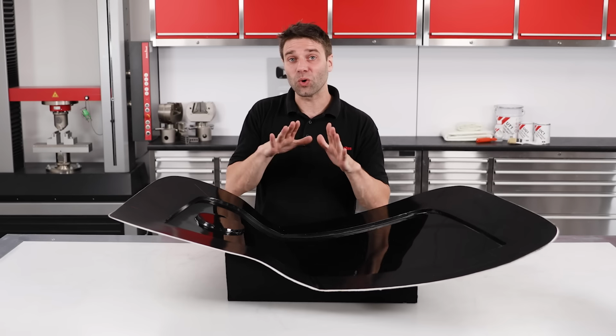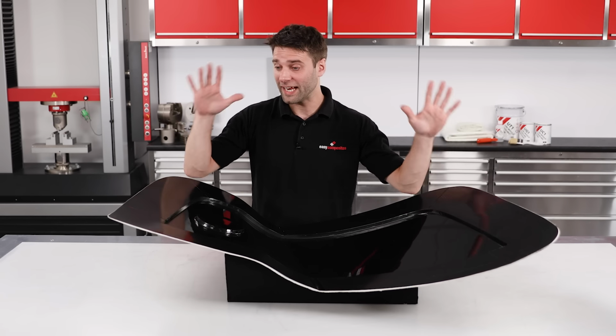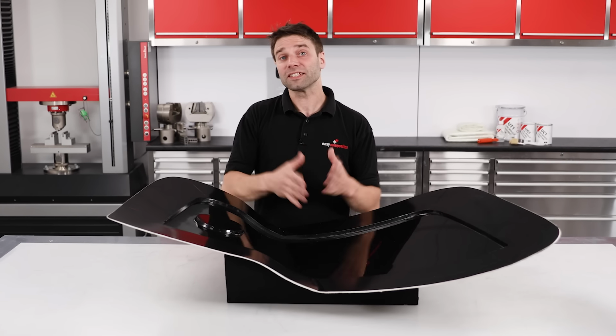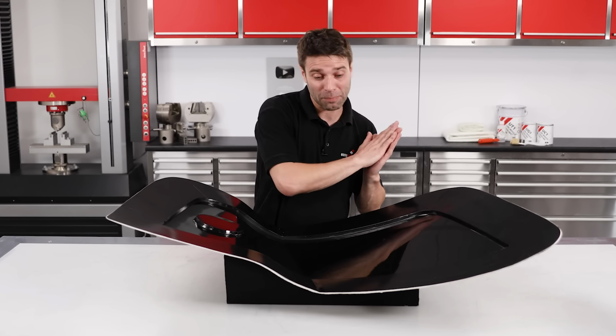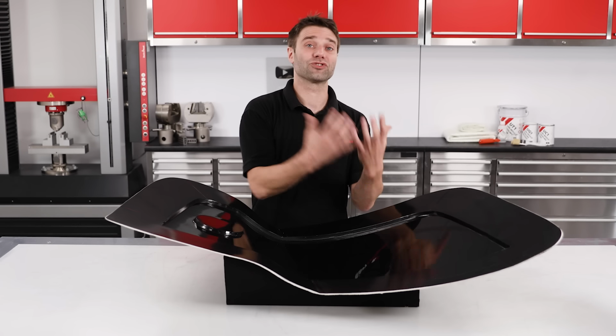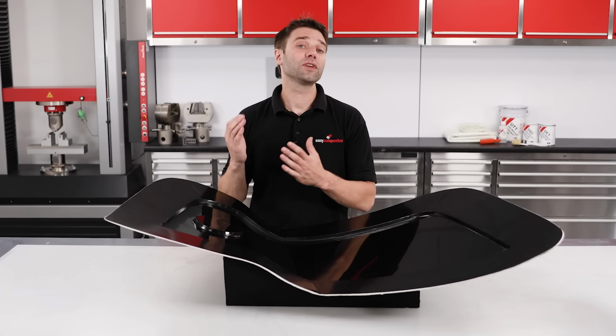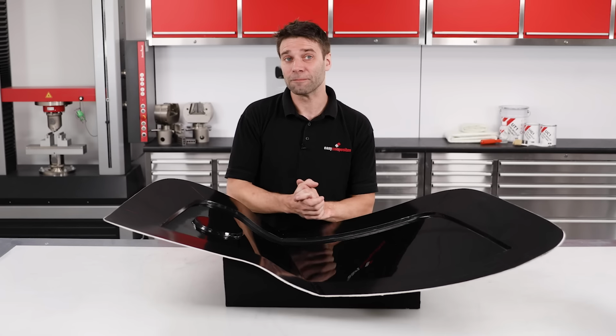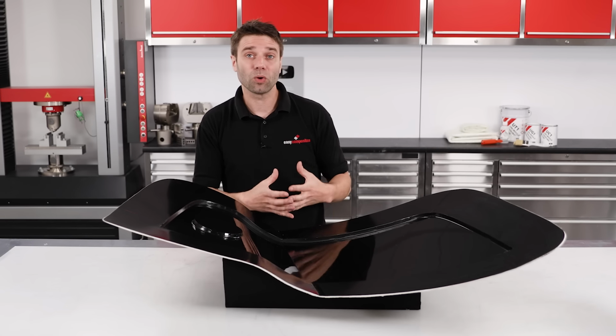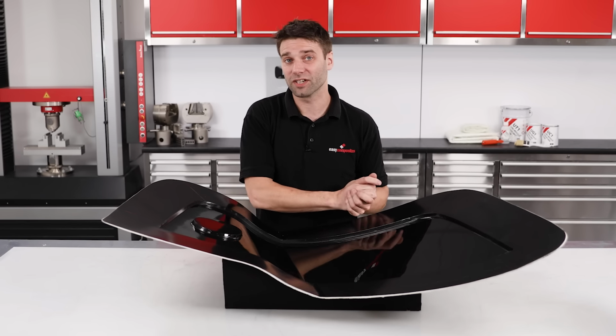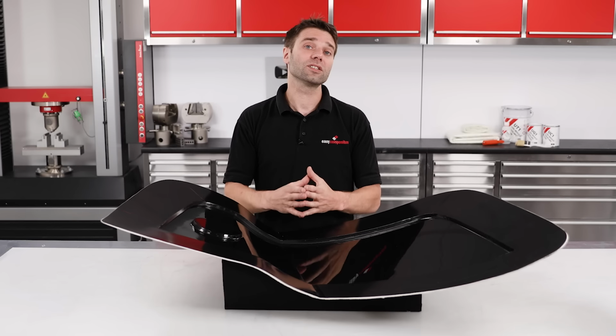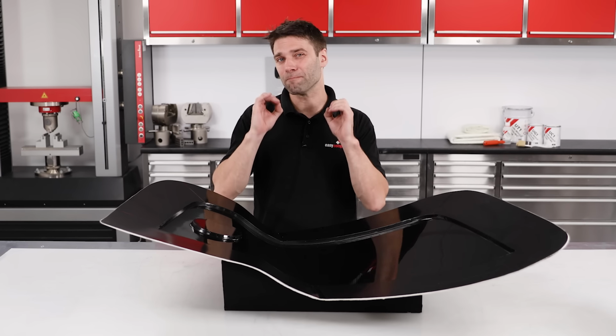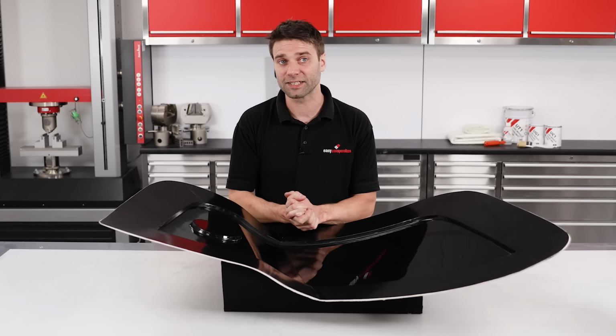Okay, so now that this is all trimmed up, we have what is effectively a finished mould. And while in certain situations you could simply apply a release agent to this and put it straight into service, there are a few final steps that might be needed. Firstly, if you plan to use this mould at temperatures above 40 degrees C, then you will need to conduct a post-cure to get that maximum service temperature from the system.